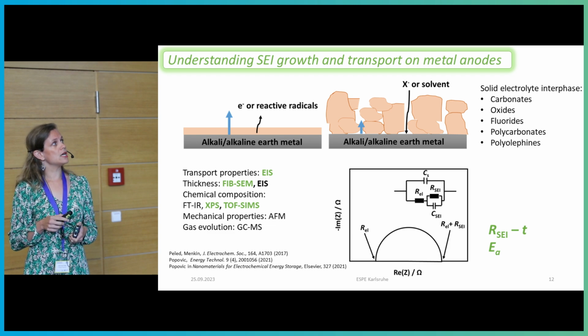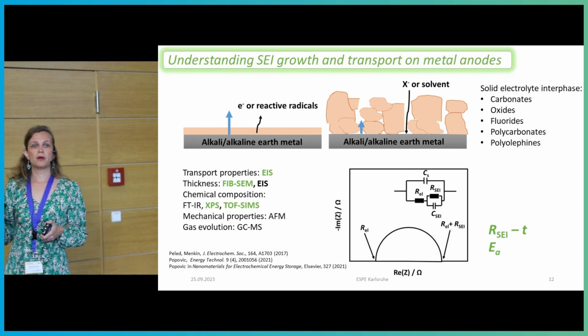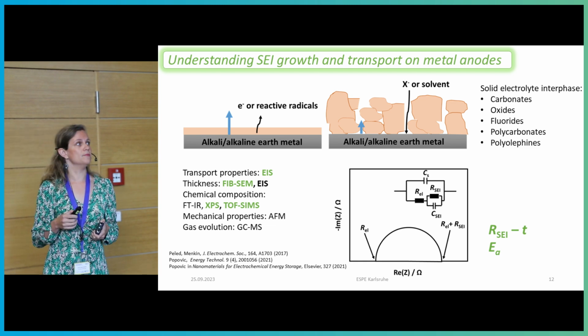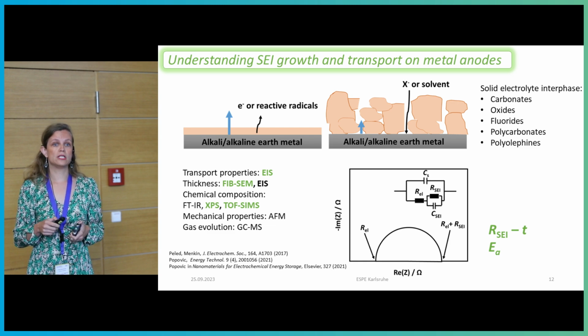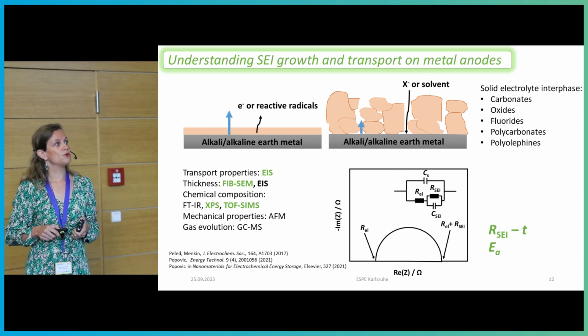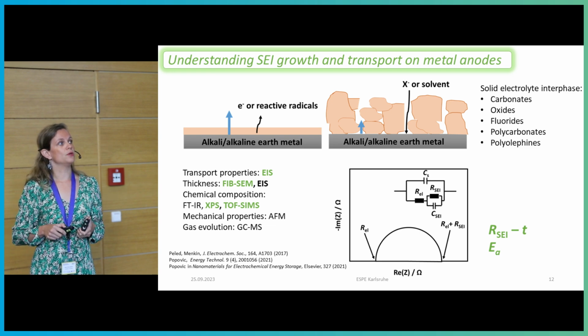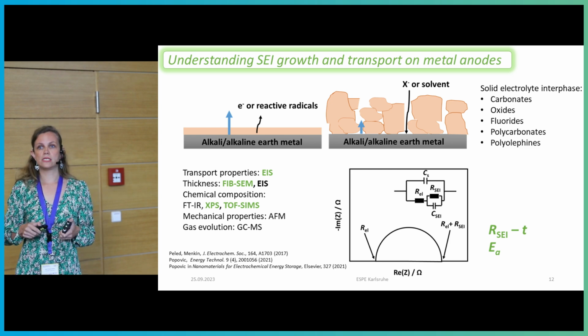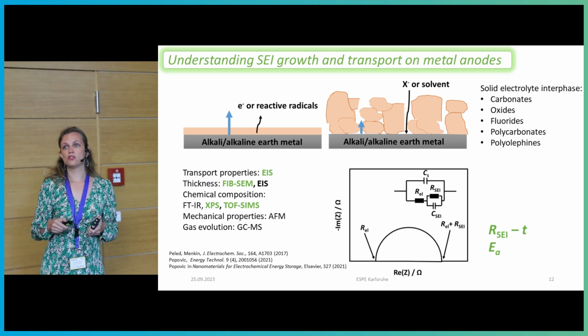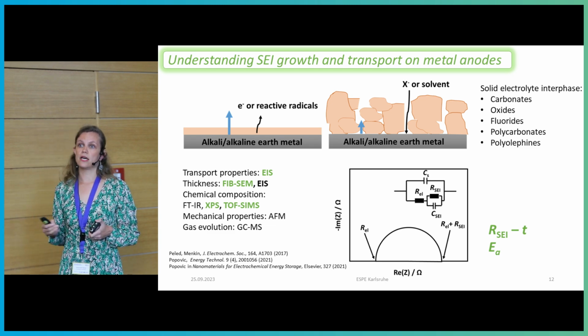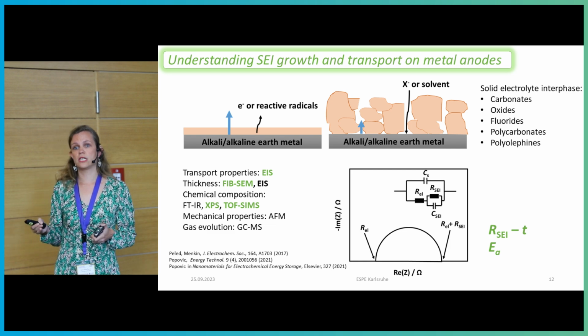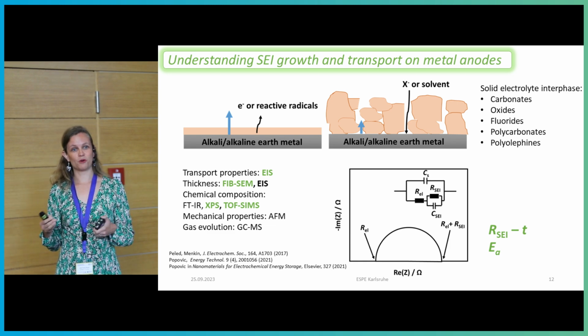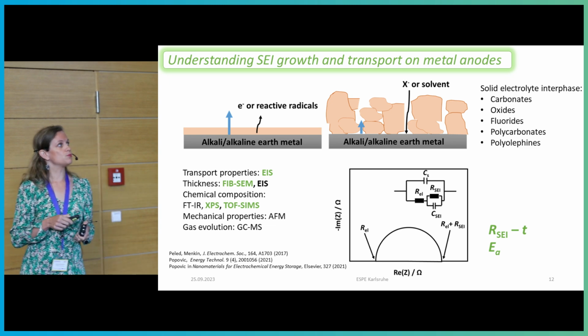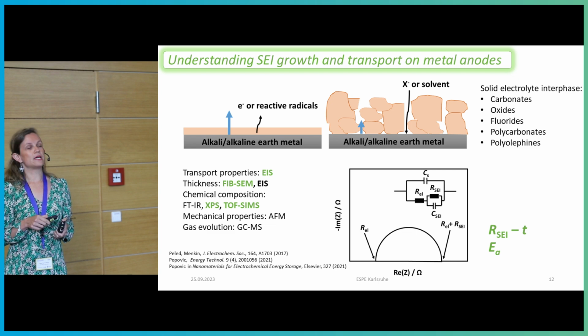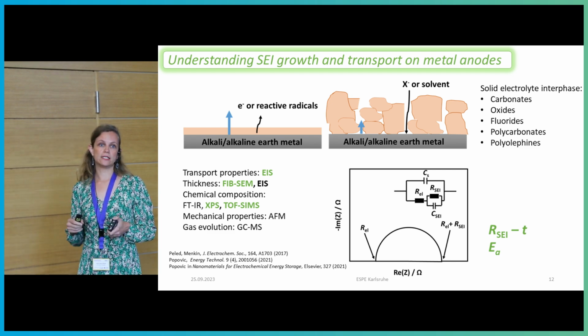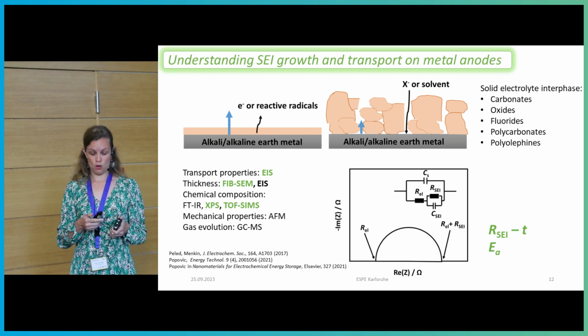So what we have been doing is trying to measure the evolution of this SEI in time. A very nice way to do that is impedance spectroscopy in symmetric cells, where, as you can see from this medium frequency semicircle, we can extract both the resistance of the SEI changing in time, but also the activation energy of this process, and see how this SEI evolves in time. And then, of course, we have to understand what happens chemically and morphologically in order to make any kind of conclusions. That means we have to do quite a lot of FIB-SEM, XPS, and TOF-SIMS, and these are not easy techniques to apply to alkali metals, as we all know.